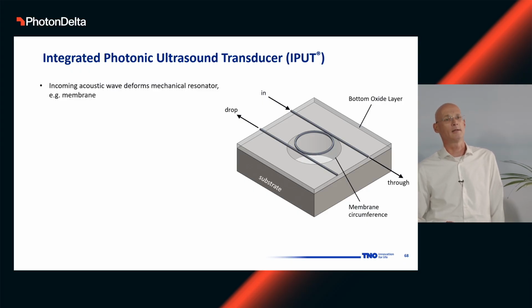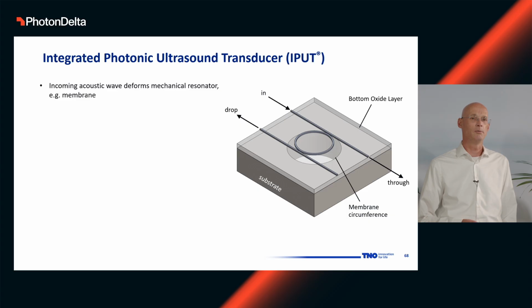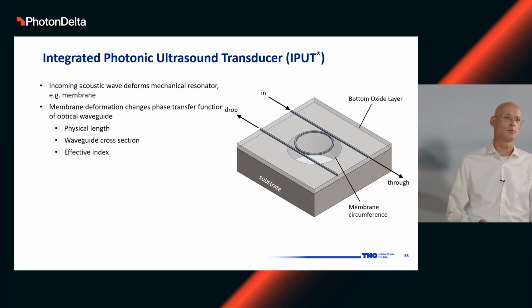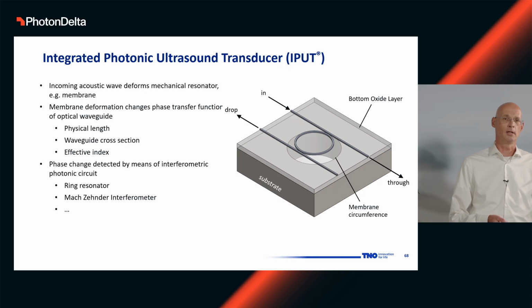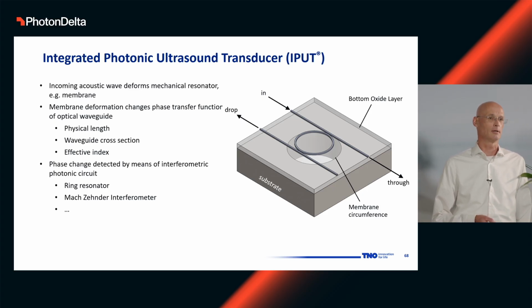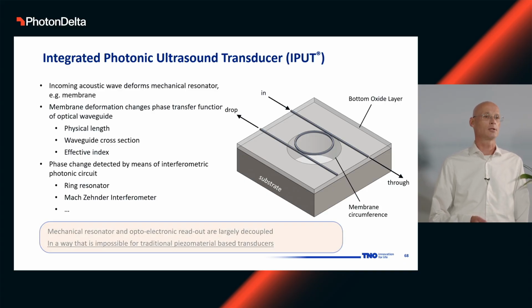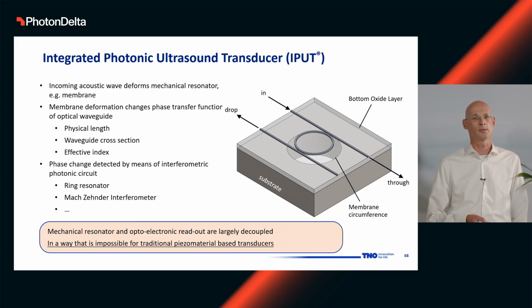What we do is we take, in this case, a ring resonator, which sits on a buried oxide layer on a substrate, so a typical photonics platform, and we remove the substrate below the ring resonator, so that the ring resonator now sits on a membrane. And what happens is that the membrane deforms because of the acoustic signal, and as a result, the ring resonator waveguide will change in physical length, but also the waveguide cross-section and material effective index will change a bit. As a result, there will be a change in the optical phase in this ring-shaped waveguide. And when you include this in a ring resonator or an interferometer, you can transfer that to an intensity, which you can detect by means of a detector.